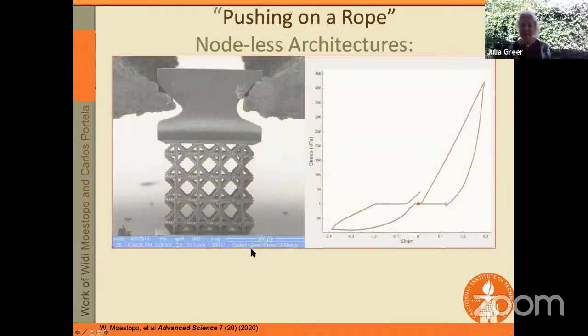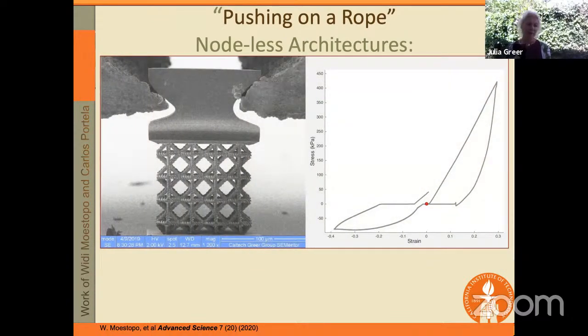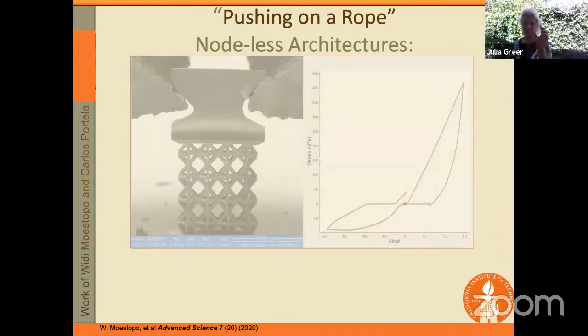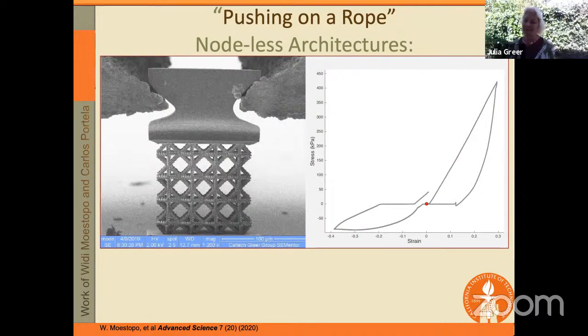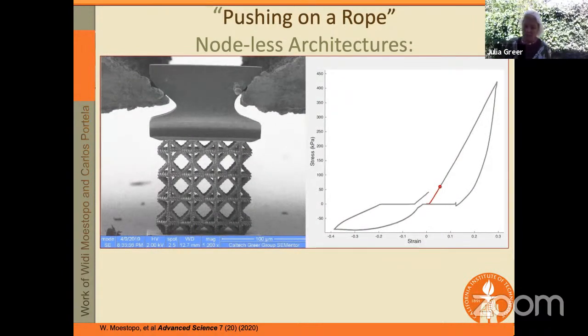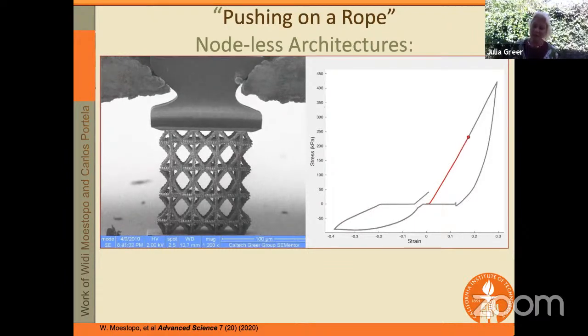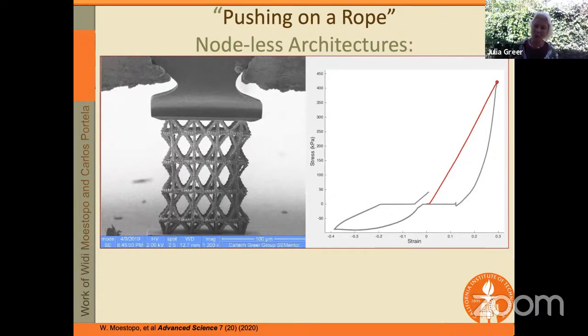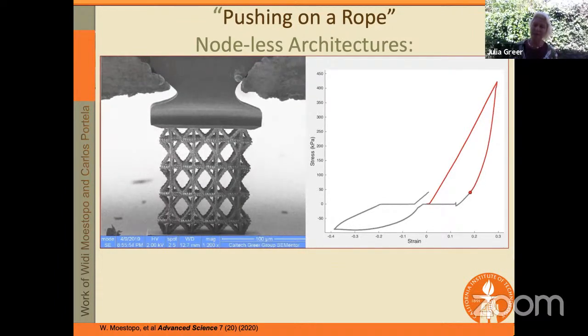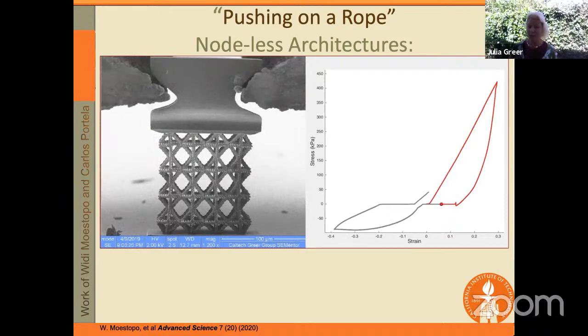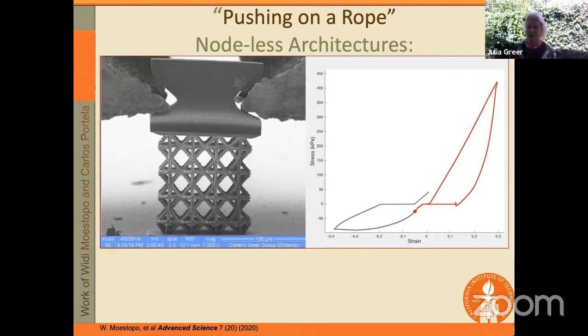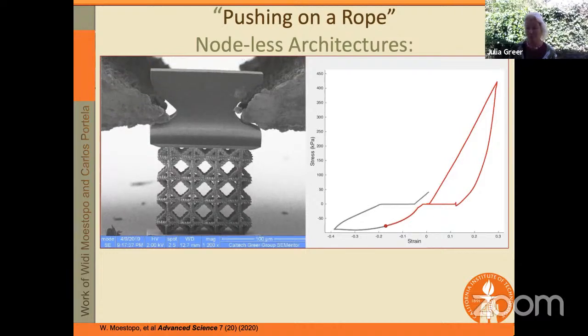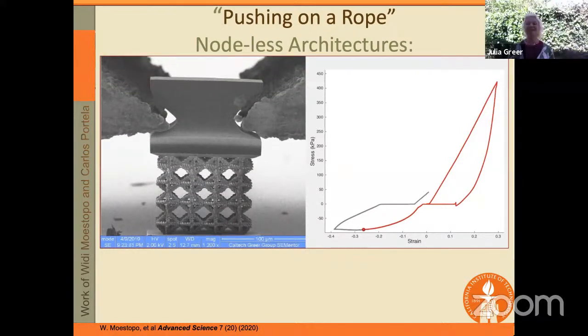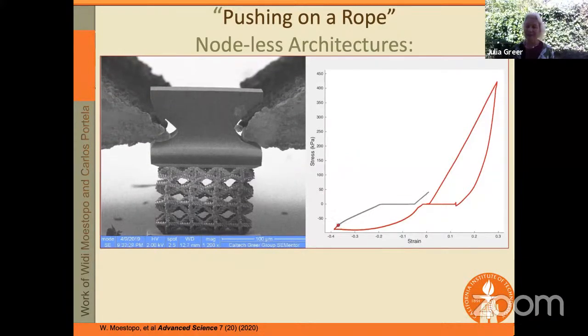Now, as you can see, one common feature of all the architectures I had shown you up to this point was the presence of the so-called nodes, the junctions where the beams meet. So to avoid the nodes, what we've designed is a woven architecture. And what you can see here is effectively a rope. And so these are comprised of various strands like a braid or a spiral. And so at the nodes, we no longer have any of these junctions. And look at what's happening. We're able to push on a rope effectively. So we're able to tense it first and then to compress it. And you can see that it offers resistance in both directions.